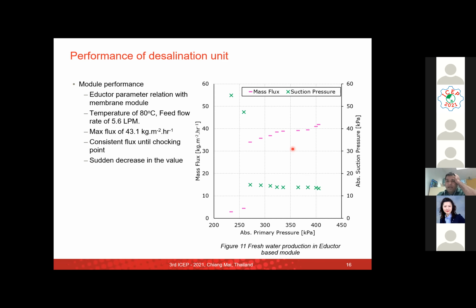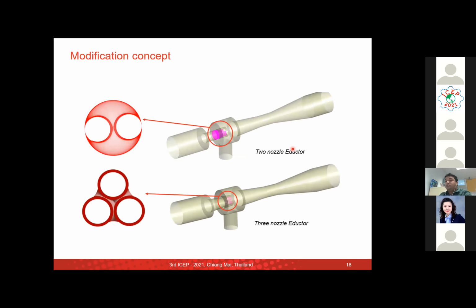So we did some exergy analysis to see where the maximum amount of exergy was being destroyed. And we could see that the maximum exergy destruction was occurring in this region, where the vapor and the liquid come in contact with each other. So what we did was modify this region by increasing the interface interaction area with 2 nozzles and 3 nozzles, so that we could increase the interface interaction area by 1.4 times and 1.7 times.